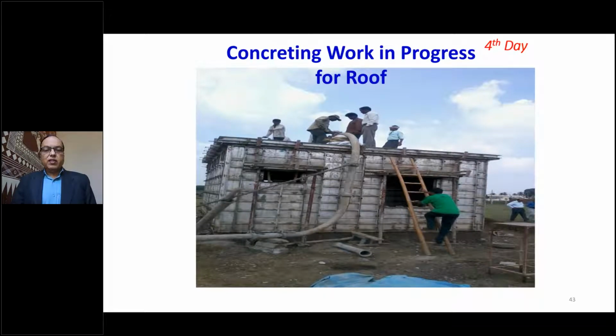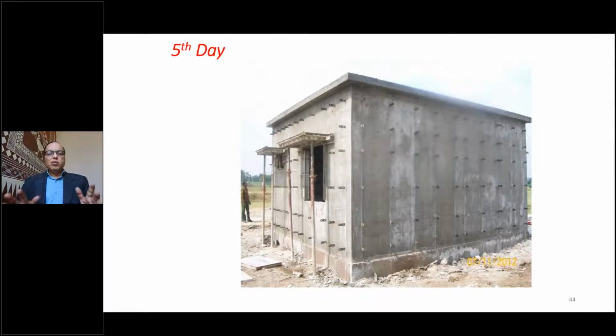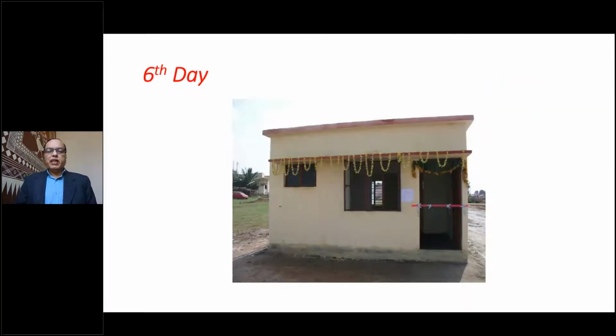Therefore, fourth day concrete was put, and the fifth day, after 24 hours, we removed all the side shuttering. Only the vertical props were kept for 1 more day. And after that 6th day, they were also removed, and 1 coat of painting was done on the 6th day, and the house was ready on the 7th day morning for opening.